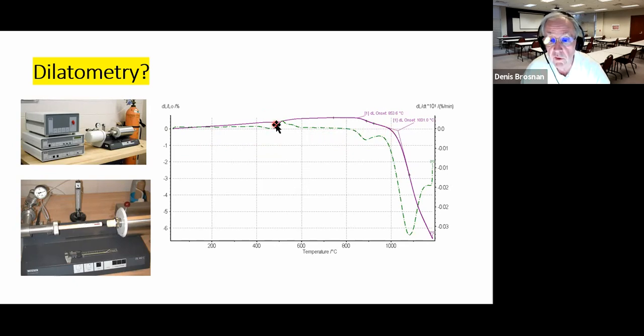You'll learn in this course that there's some inflection points here. The derivative of length versus temperature is shown here. Delta L over L, or derivative of length over unit length, change in length per unit length versus temperature. When it goes up, it shows an inflection point. So that's going to be here right around 500 degrees Celsius or so. And you'll become very familiar with identifying that that's probably due to the quartz inversion, which goes from alpha to beta quartz at that particular point in time. Don't worry about the definition of alpha and beta quartz. It's just an internal change in the ceramic for today's purposes.